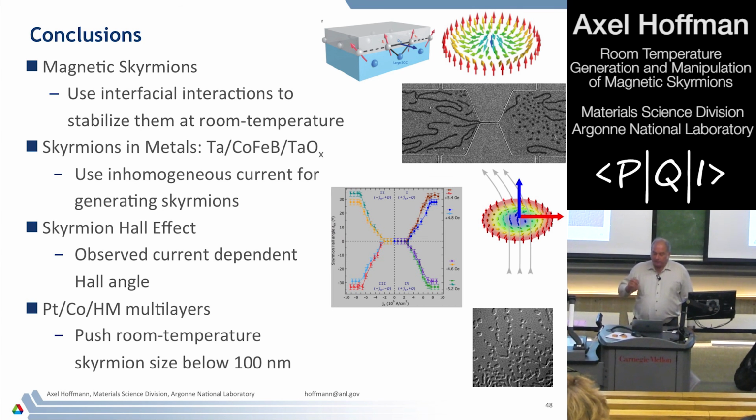Now there's one more thing that I should say. When we have the skyrmions as large as what I've shown here, then all the forces that move them are essentially exactly the same as the ones that move domain walls. The fact that they have a distinct topology just changes the direction in which they move, but other than that, they don't move any faster because of it.